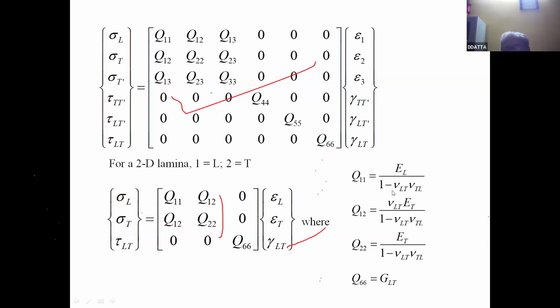So all these Qs can be evaluated in terms of the Young's moduli of an orthotropic material. Q11 is this and this. Here, 1 minus nu LT and nu TL. Nu LT is a major Poisson's ratio. Nu TL is a minor Poisson's ratio. They have relations. So there are actually 1, 2, 3, 4 and 5 constants visible. But nu LT and nu TL are not independent, they are dependent. So basically, in an orthotropic lamina, in the principal material direction, there are 4 independent constants, I should say. What are they? EL, ET, nu LT, and GLT. These four. Nu TL is a function of nu LT, EL and ET.